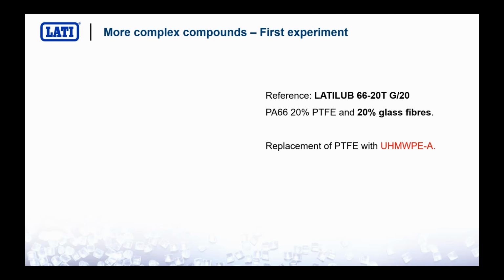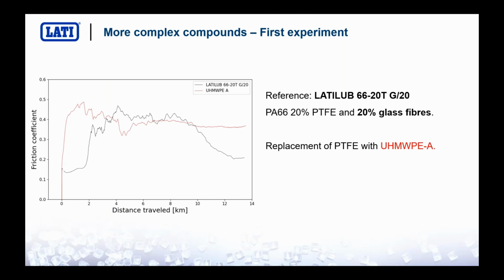fiber. And we tried to replace all the amount of PTFE with ultra-high molecular weight polyethylene type A. This is the plot, and as you can see, after a starting point, a running step, more or less the average of the friction coefficient is comparable to the material with the black one, so the material with PTFE. So also in this case, this kind of additive seems to work in a good way.